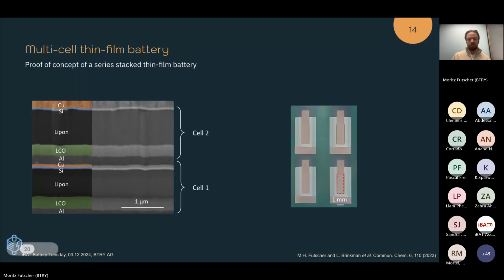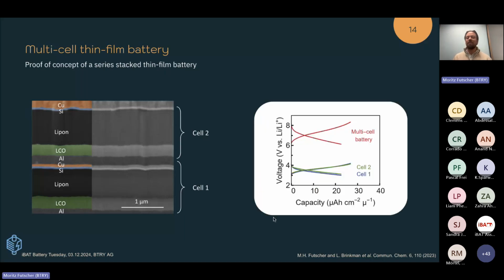And here you see the performance of these cells, where you see in green and blue what happens if we cycle these cells individually from each other. And then if we cycle them together, we see that the voltage doubles, as we would expect if we electrically connect such cells in series with each other. So this means that also the energy of this cell has doubled without additional substrate contributions.